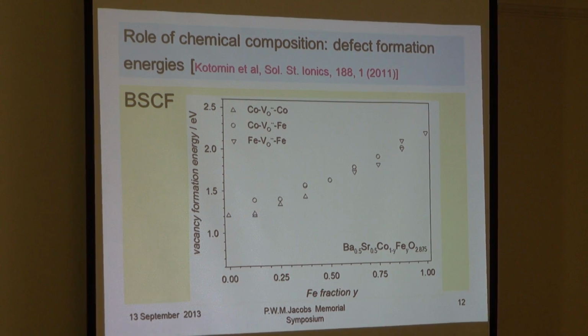of iron when we have different ratios of cobalt and iron. So the iron concentration changes. So it's pure cobaltite, and this is pure iron, essentially. And this is just the vacancy formation energy. And you can see that vacancy formation energy has a very clear trend with composition in the B sublattice. So for cobaltite, the formation energy could be 1.2 electron volt, and it increases practically twice when it's iron rich. So it means that cobalt-rich material essentially has much lower formation energy.